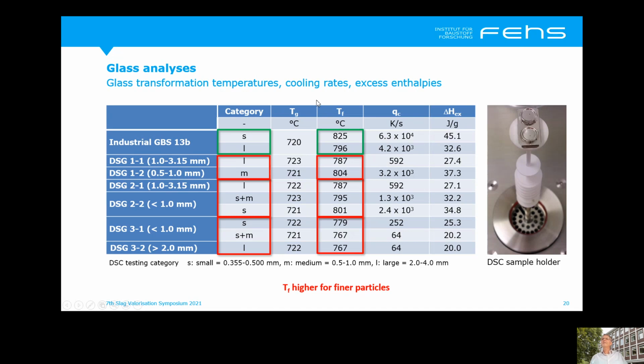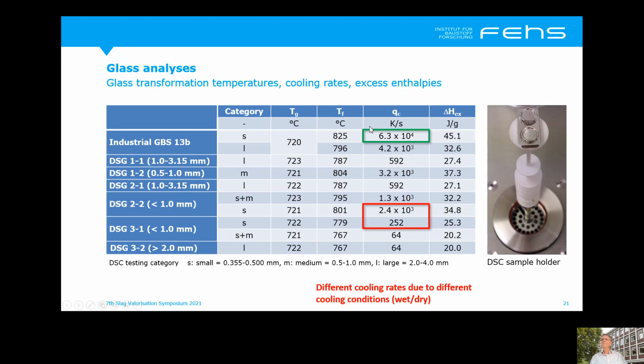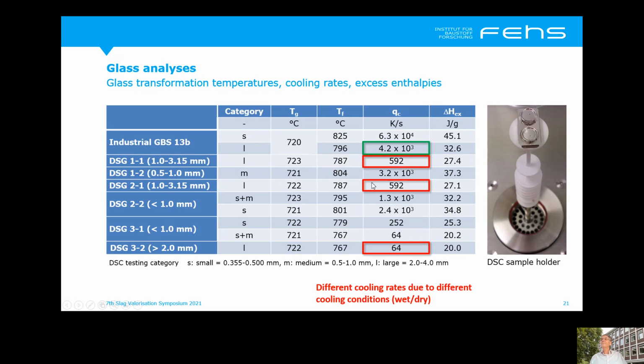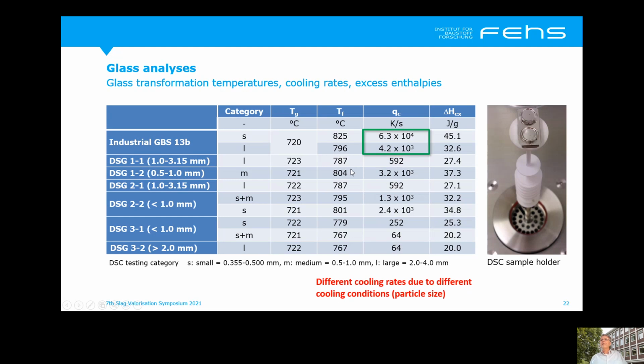The fictive temperature correlates with the cooling rate, as I explained. Looking to the same particle size, the cooling rate for the wet granulated slag is much higher compared to the dry granulated slags, despite the fact that the viscosity is very similar. And also the same effect for the large particles. Comparing bigger particles and smaller particles in general, you see that also for the wet granulated blast furnace slag, larger particles are cooled down more slowly compared to smaller particles. The same effect for the dry granulated slags.